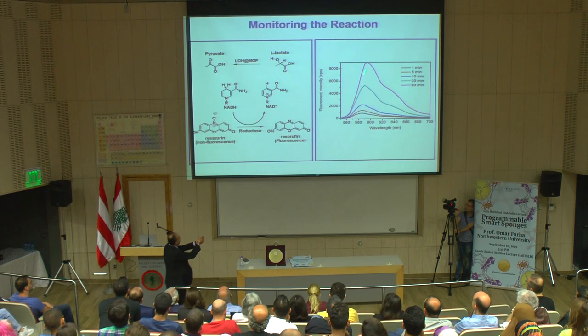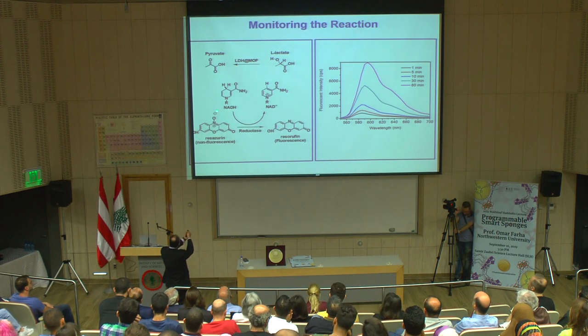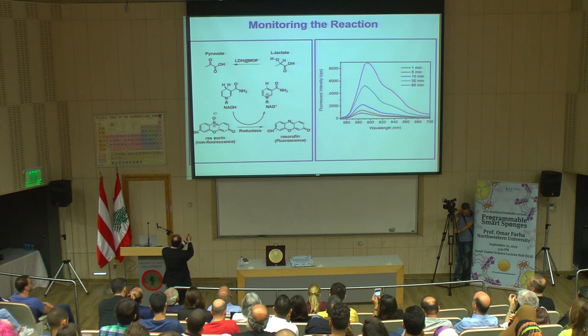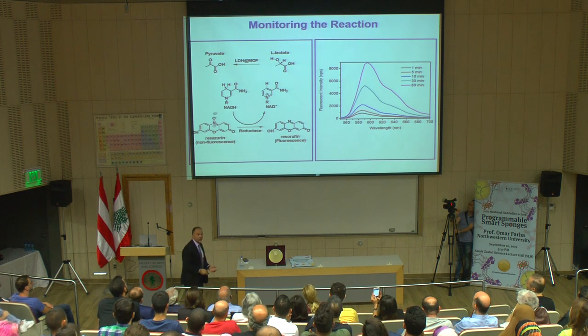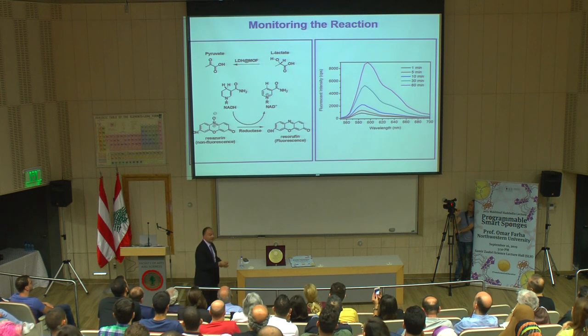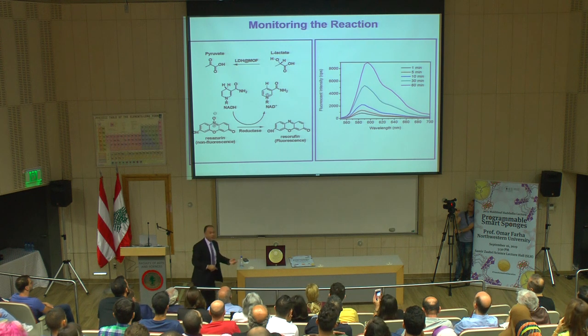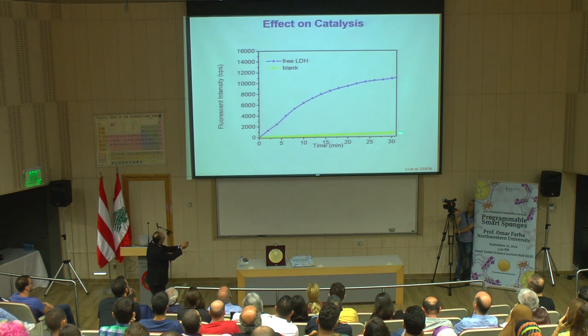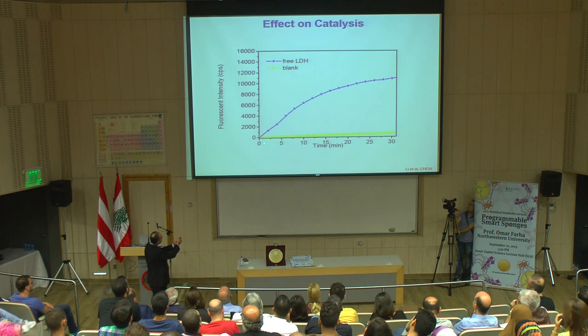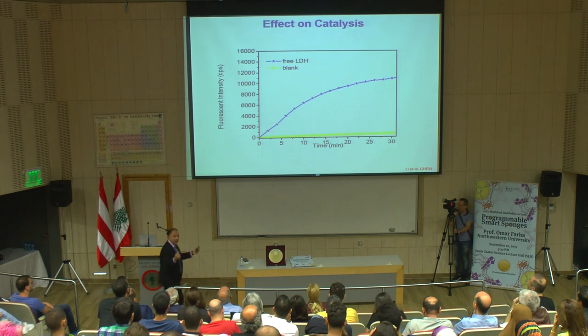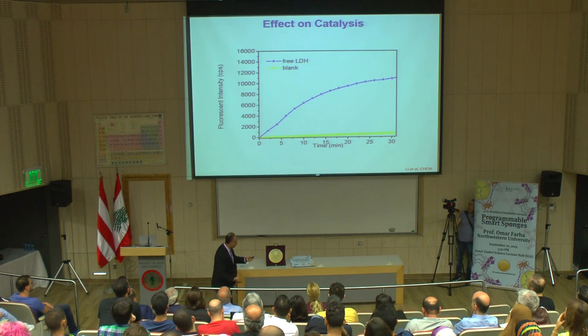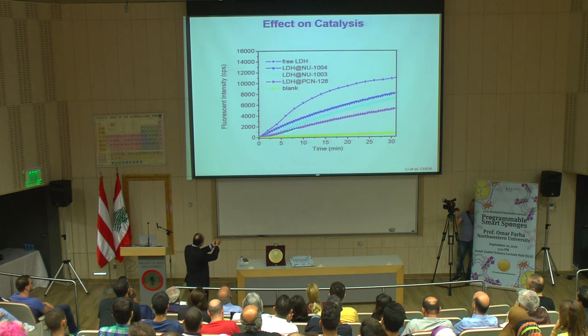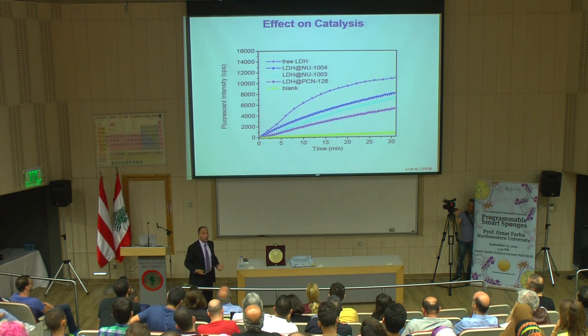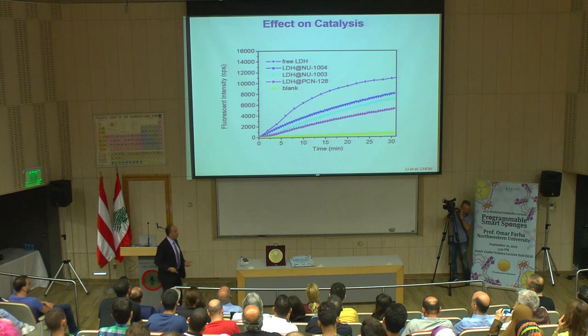How do we test the reactivity of these materials? This takes pyruvate to lactate, but now we use a non-fluorescent dye, and when the reaction happens, for every turnover it gives you a fluorescent signal, and we start counting the fluorescence. This is without any catalyst. This is the homogeneous catalyst, with everything dissolved in solution. If you have the smaller channels, you have slower kinetics for our composite.